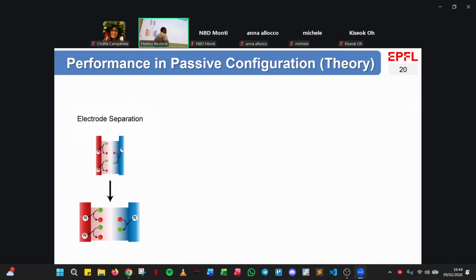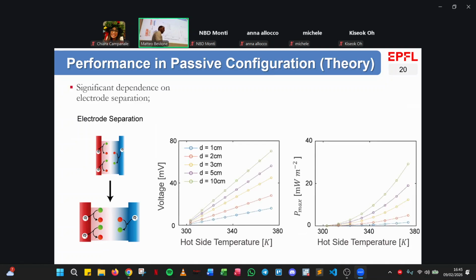So a very important thing that I wanted to understand is that in literature, it's everywhere present the study of how the performance changes with the electrode separation. So how thick you make your cells fundamentally. The point of this was that in literature, they say this is absolutely independent. The power you produce is absolutely independent on the thickness of the cell itself, which for me was maybe possible in a liquid, but in a gel, that's pretty odd, especially if we are not in an active configuration. So what they were doing is to fix the temperature of the two sides and then having fundamentally the same results. But for me, the thing was not exactly like that.